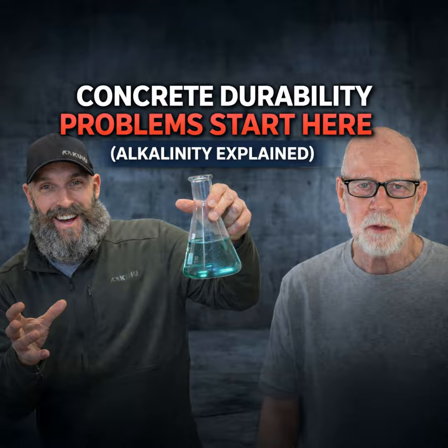And even though it's not even close to 100% relative humidity, at which normal atmospheric condensation will occur, the dew point, it will begin to liquefy, and it turns into a liquid at 80% relative humidity. So that water is now captured. That's not available to be measured, because as you put something down on there, like a relative humidity probe or anything like that, it will measure 75% relative humidity. According to some experts, that's supposedly dry. Well, it can be saturated, but it's measuring dry because they misinterpreted what the salts do.